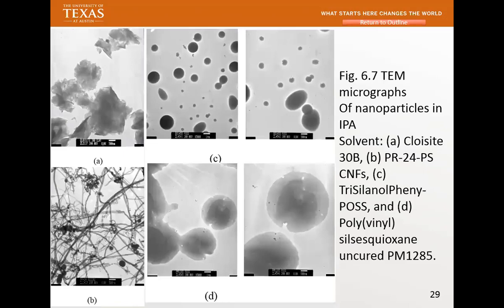The trick is this: when you see that, you cannot tell how good the dispersion is. When you cut the clay this way, you see the thickness. Then you can see how well dispersed it is. So unfortunately, you've got to cut a lot of samples in order to see this orientation. And the XY, I call XY, which is the thickness of C. If you cut a sample like that, you cannot see. You may say, yeah, they're stacked together, but it's not a good way to see how well dispersed. You need to cut it so you see the C direction thickness, and you will see. I'll show you some other examples.